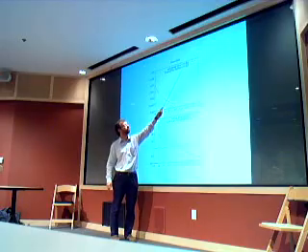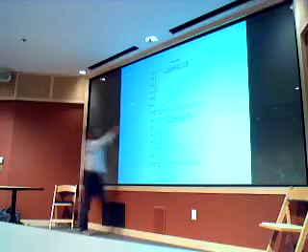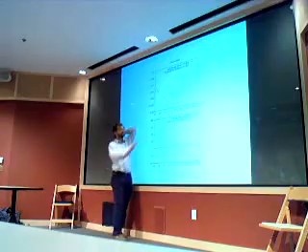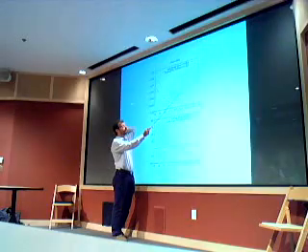So we have a calculation that is done at 18 Rydberg. Include all plane waves up to 18 Rydberg, but give a penalty to all plane waves that are above or around 16 Rydberg. Actually, already at 16 Rydberg the plane waves are penalized. This is why this curve is above the red one. Okay, so at 16 Rydberg, you are already adding a penalty, and so the total energy is larger.